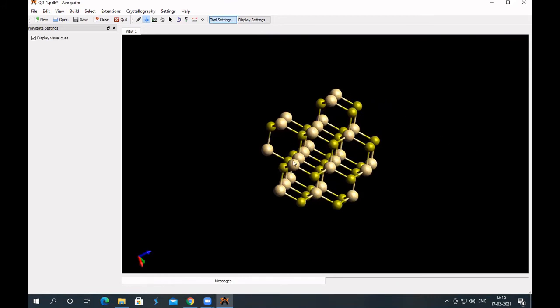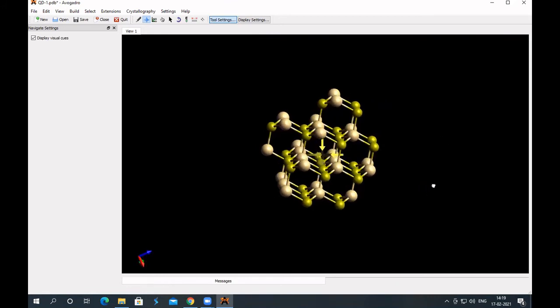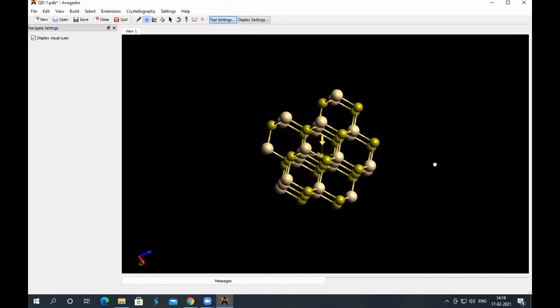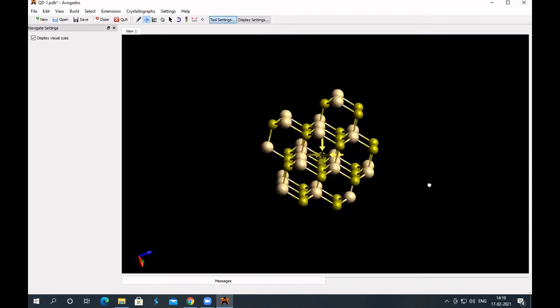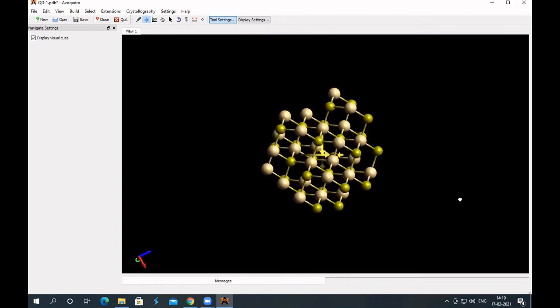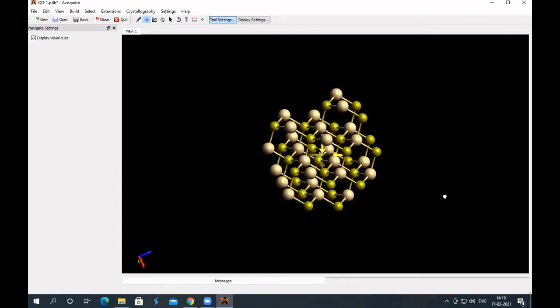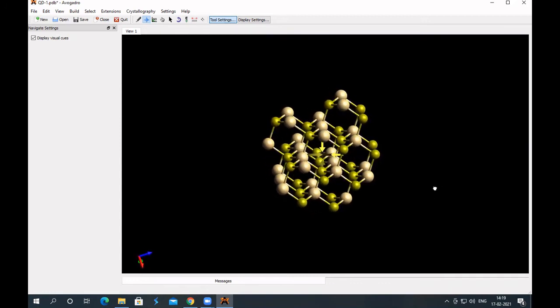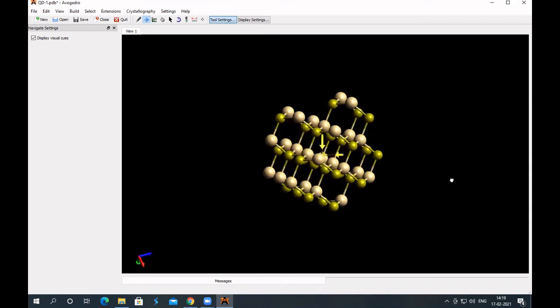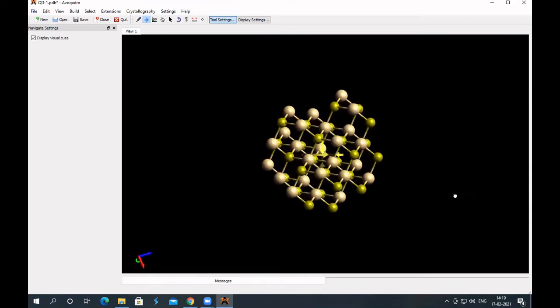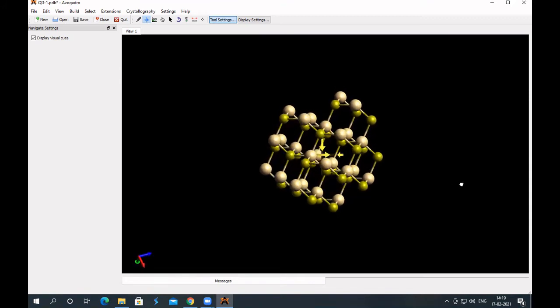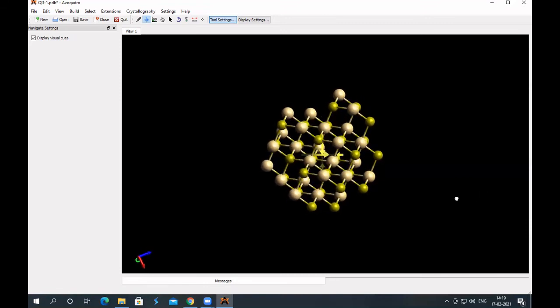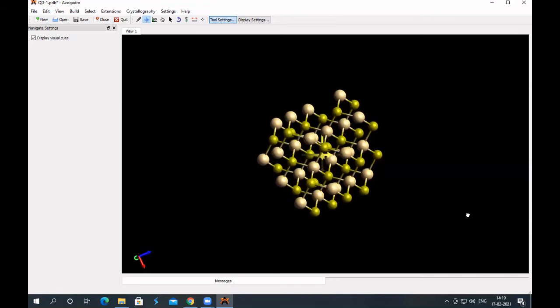Now count the number of cadmium ion and sulfide ion. The one thing which I mentioned earlier, that you have to maintain the electrical neutrality. So do it in that fashion that you have more cadmium ion, as compared to sulfide ion, so that you can further use acetate ion to make few surface ions. You can increase the coordination number from two to three, or from three to four, and so on.